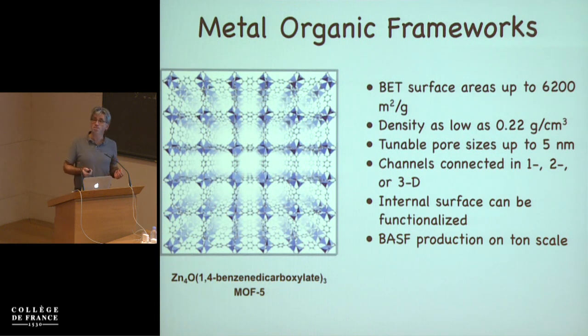If you have a mixture of, say, CO2, carbon dioxide, and nitrogen, which is, for example, in flue gases, you would like to selectively remove the carbon dioxide. Well, this is a material you can use. It selectively can absorb CO2. Then you can remove the CO2 from flue gases. That is a particular application. What is then the interest here is these materials have the world record in surface area. If you have a gram of material, it has a surface equivalent of a soccer field.